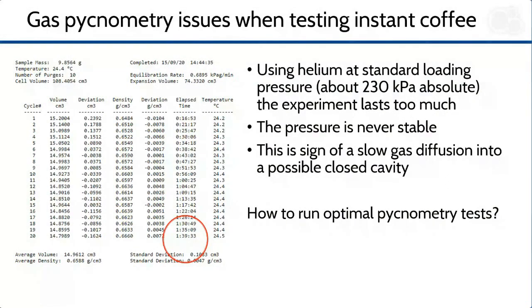This technique, using automated gas pycnometers, is generally very rapid. In case of instant coffee under our investigation, the helium pressure equilibration was extremely long. After more than 90 minutes, we could not get reliable results on the skeletal density. Long gas equilibration time after checking the leaks of the instrument are often due to the presence of closed pores that are accessible by helium with a slow diffusion process. In these conditions, the analytical parameters should be optimized because using the standard condition, the skeletal density may be variable depending on the number of analytical cycles.